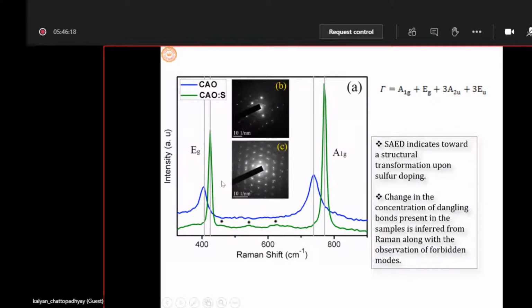You see that here the Raman active modes are A1g and Eg. In the morning we listened to a good lecture on how to find the number of vibrational modes. If you do the irreducible representation, you can find these; the Eu and Au are acoustic modes. These two are the Raman active modes of such a system, and these are the peaks. The blue one is for the pristine sample. Look at the broad nature of the peaks, and also you can see the higher background.